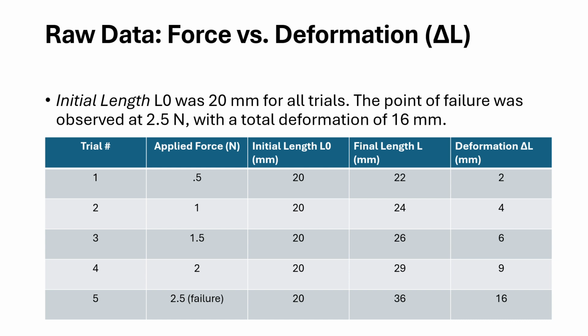And here is the data table. The initial length L0 was around 20 millimeters for all trials, but the point of failure was observed at around 2.5 newtons with a total deformation of 16 millimeters. So for each trial, I weighed and put on each weight with precision, where I went up in increments of 0.5 newton. So for trial 1, obviously, I went for 0.5 newton and it changed 2 millimeters.